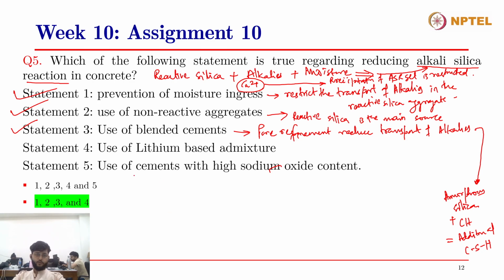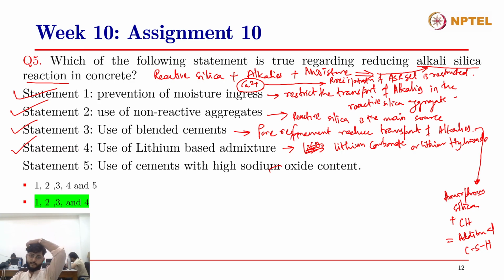The fourth statement here is use of lithium based admixture. Generally, in order to mitigate the risk of alkali silica reaction, we use lithium carbonate. I don't exactly remember the stoichiometry of it, so I'll just write it: lithium carbonate, or lithium hydroxide. And what the lithium based admixtures do is they replace the alkalis, Na+ or K+, present in the ASR gel and make the ASR gel soluble.